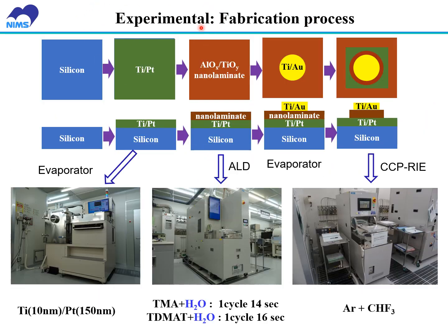Next, I will show the experimental part. This is the fabrication process for the metal/ATO nanolaminates/metal capacitors. The first step is the bottom titanium-platinum electrode formation using the evaporator technique. Then the ATO nanolaminates were formed using the ALD technique with the precursors of TMA, TDMAT, and water vapor. Then the surface titanium-gold electrodes were formed on the nanolaminates. Last, the nanolaminates were etched using a CCP-RIE system to open windows for the bottom titanium-platinum electrodes.